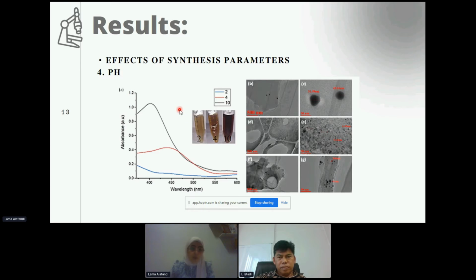The fourth and most crucial parameter is pH. So here, the pH of coffee extract is 4. So we see there's formation of silver nanoparticles without any adjustment of pH. But when pH is 2, when we added an acid, we see no formation at all of silver nanoparticles according to the UV-Vis analysis. And with pH 10, we can see high formation of silver nanoparticles, and the peak of the curve is shifted to the left, which means it's a smaller wavelength, which means we assume it's a smaller size of nanoparticles formed here.